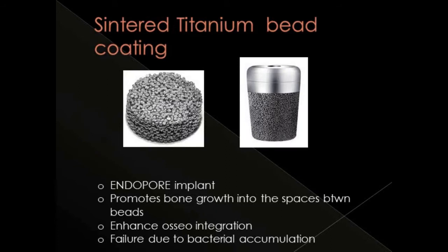Finally, sintered titanium bead coating: the Endopore implant is a Canadian implant fabricated by sintering small micrometer-size beads of titanium onto the surface of the titanium core. This promoted bone growth into the spaces between beads, enhancing osseointegration. However, the main disadvantage was bacterial accumulation under the beads — once bacteria enter the coating they can freely colonize all the way to the apex of the implant, causing implant failure.